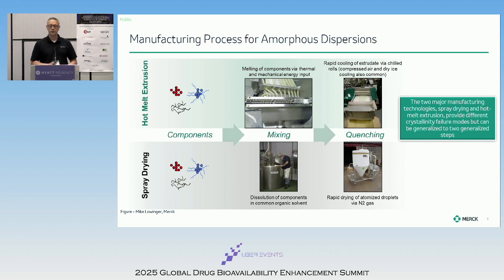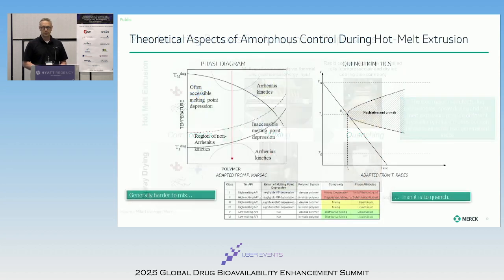Whereas in the case of spray drying, you're going to do your mixing step in a common organic solvent, which is actually fairly easy to do in many cases. In some instances, there can be a little bit more complexity depending on the solubility profile of your components in the formulation, both active and excipients. But it's really the quenching step in spray drying that creates the most challenge, because not only are you going to lock in the overall homogeneity of that dispersion, but you actually lock in the particle attributes as well, which can have a role in terms of downstream performance.